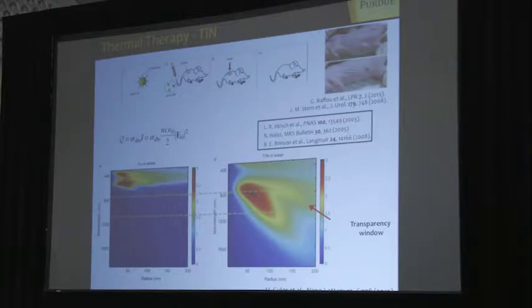Then you irradiate it at the wavelengths which are in the biological transparency window, and this is between 800 and 1100 nanometers, you excite these surface plasmons, you locally heat it up and destroy cancerous tissue, and it does work.